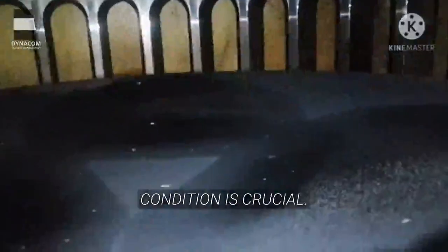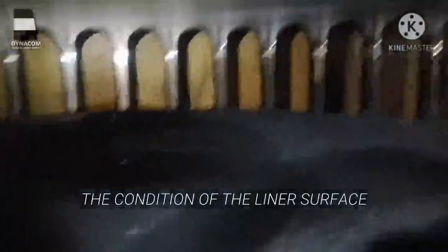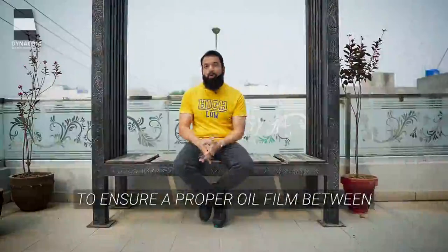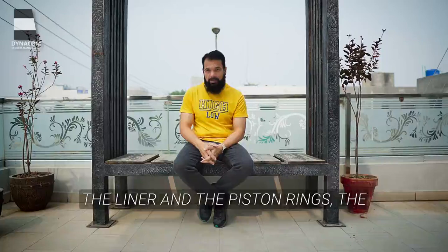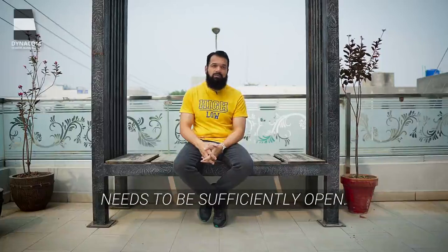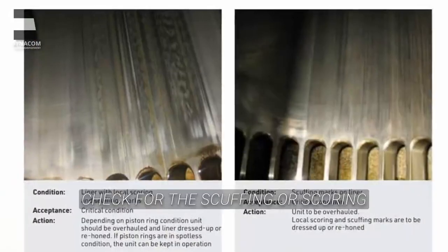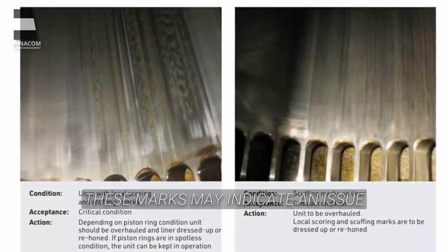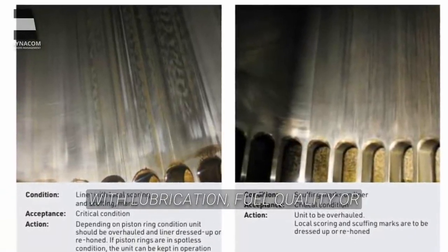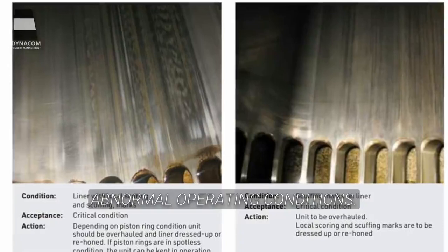Checking the liner surface condition is crucial. The condition of the liner surface plays a significant role with regards to scuffing. To ensure a proper oil film between the liner and the piston rings, the liner surface structure needs to be sufficiently open. Check for scuffing or scoring marks on the cylinder liner. These marks may indicate an issue with the lubrication, fuel quality, or abnormal operating conditions.